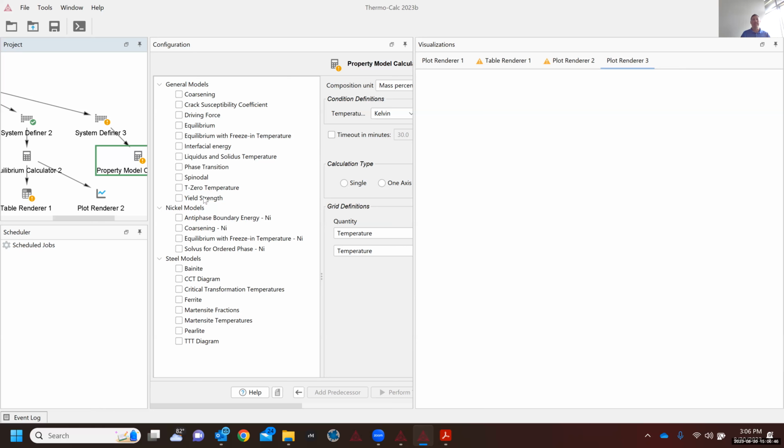So I recommend that if you want to calculate strength of your material, you perform your thermodynamic and microstructural evolution calculations in here, get your precipitate size distribution for solid solution elements, and then take that information and put it in a strength model using the same basic models that are in here that you would find in, say, a mechanical metallurgy book, some other strength models, because I don't think they've got there yet using these. I haven't used it in the 2023B version yet, but the last time I tried, I got a yield strength of like 10 megapascals for something, which was a little lower than I would have expected, or a lot lower.